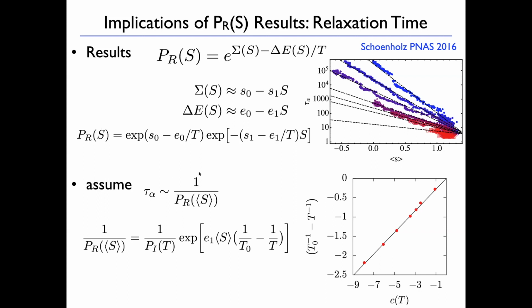And if I look at the equation that I have for the probability of rearranging as a function of softness, which I showed you before, and now I just make a simple assumption. I just say the relaxation time is 1 over the probability of rearranging evaluated at the average softness at that temperature. Then I get an expression that looks like this. It's e to the average softness times 1 over T0 minus 1 over the onset temperature, minus 1 over the temperature.